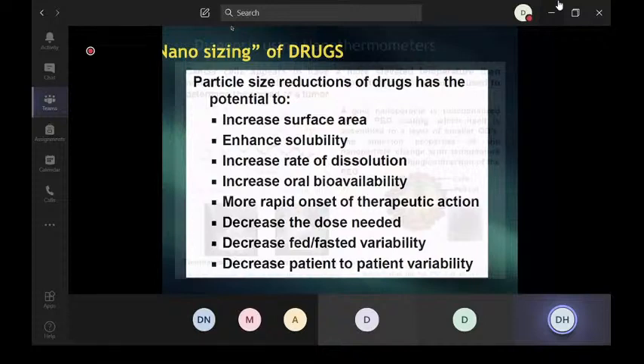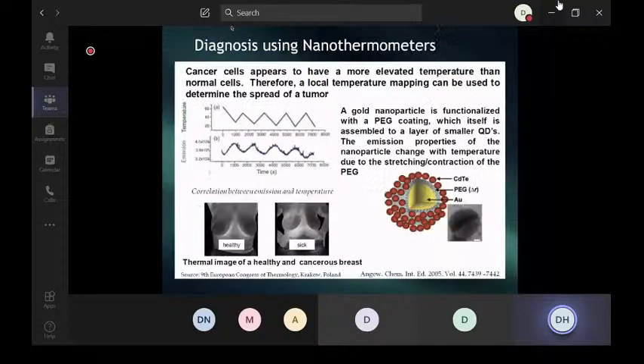But the available technique is smaller quantum dots, which is a very expensive method and expensive technology. So now with these kinds of carbon nanospheres, you can reduce the size of the nanoparticle. As I already told, we synthesized 20 to 30 nanometer. Recently, we published a paper where we synthesized the nanoparticle using a different technology, where we were able to reduce the nanoparticle size to less than 10 nanometer.